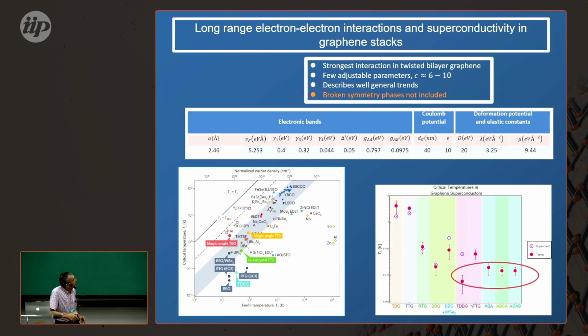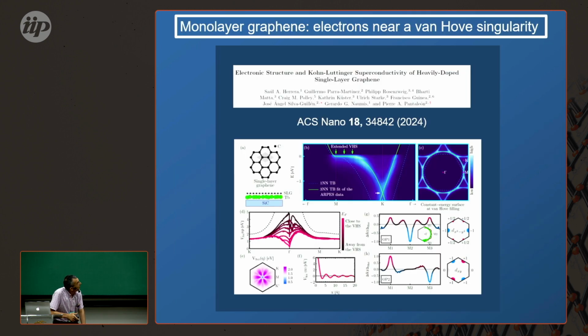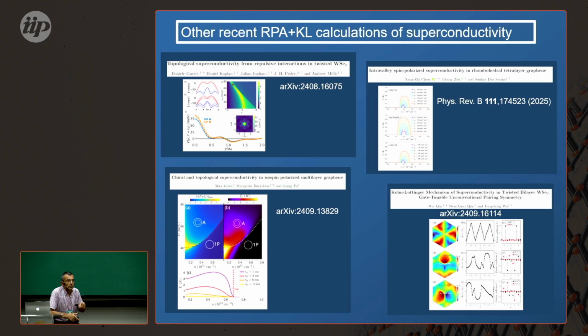I must say that when we found a very low critical temperature, like in some untwisted system, we cannot exclude the possibility that other mechanisms may play a role, obviously. And this is a prediction. We were collaborating with guys in the Max Planck in Stuttgart, and they've managed to dope graphene to the Van Hove singularity. They haven't looked for superconductivity yet, so we are predicting that there will be some superconductivity similar to the work Andrei Chubukov and Leonid Levitov did.